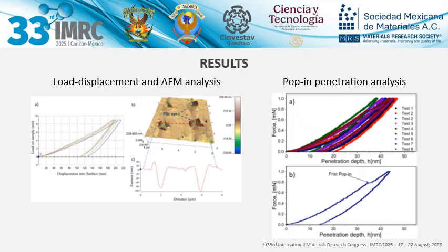Pop-in penetration analysis. At low loads, the pop-in phenomenon, representing the transition from elastic to elastoplastic behavior, was identified. This analysis complements the mechanical data and confirms that aluminum doping improves deformation resistance without compromising material integrity.